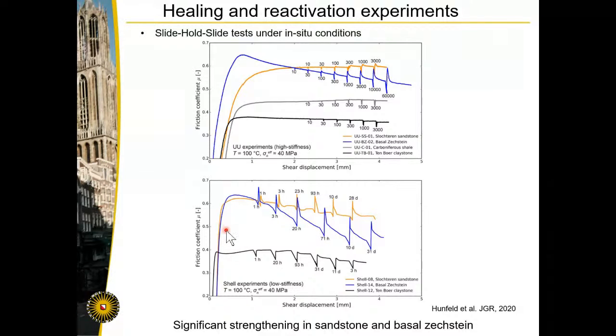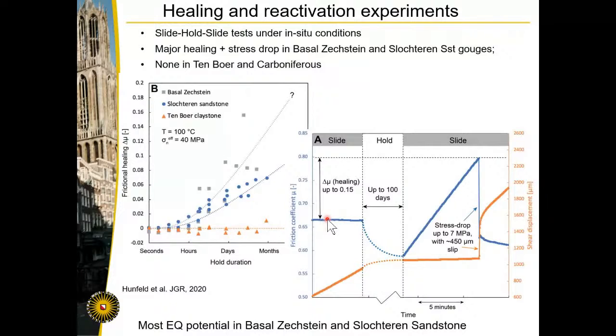Now, we also did some experiments at a really long time scale. These are the longest holds that have ever been done, up to 3 months even. And we can see that this strengthening actually continues. We can quantify this change in coefficient of friction and then plot it as a function of the hold time. And that's what's shown here. Here's the hold duration. The orange is the clay-rich rock. You can see that pretty much the re-strengthening is zero, whereas the sandstone and the basal Zechstein show this very pronounced re-strengthening, up to a friction increase of 0.16.